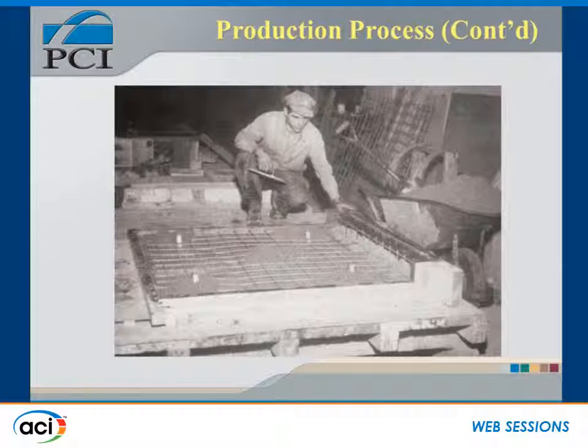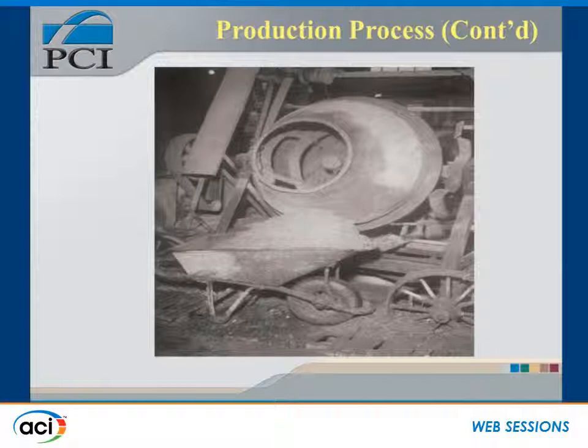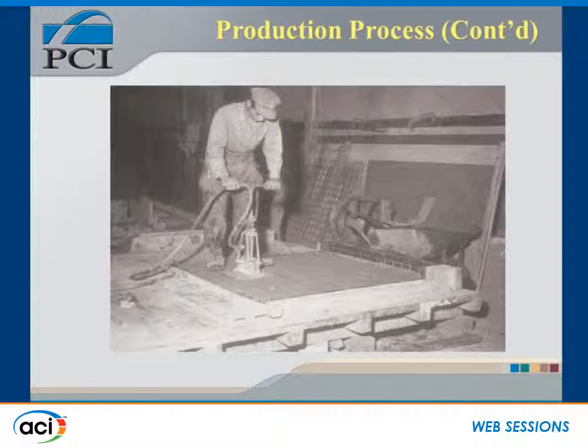The reinforcing mesh was held in the proper position in the middle thickness of the slab by small mounds of the backing mix under the mesh. It was important to keep the mesh, obviously, in the proper position to prevent corrosion of the steel. A batch of the backing mix is shown just discharged from the mixer. Note that this mix is less stiff than the facing mix. The backing mix is then placed and vibrated. Again, it's either a plate or a grate vibrator.